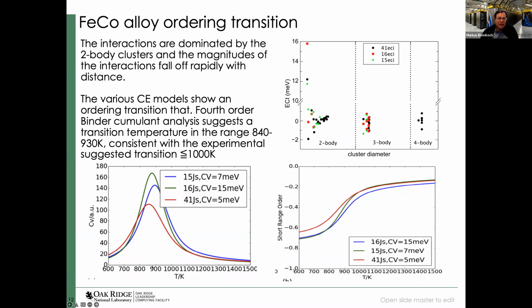Doing this analysis, we ultimately find the transition temperature to be somewhere in the range of 840 to 930 Kelvin, which is consistent with the experimentally suggested transition just below 1000 Kelvin for this system.